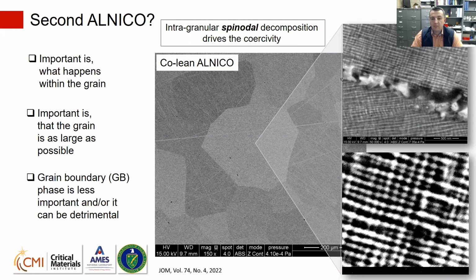And this is one of the magnets which doesn't need powder metallurgy to develop extrinsic properties, because it develops its extrinsic properties through the spinodal decomposition. And the spinodal decomposition is an intragranular process. So basically within the singular grain, you develop your microstructure, and that microstructure is responsible for your extrinsic magnetic properties. You don't care very much about grain boundary effects.